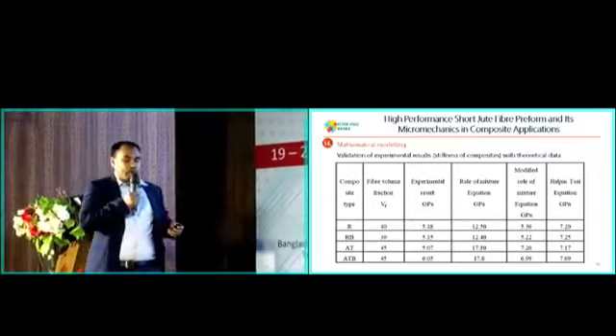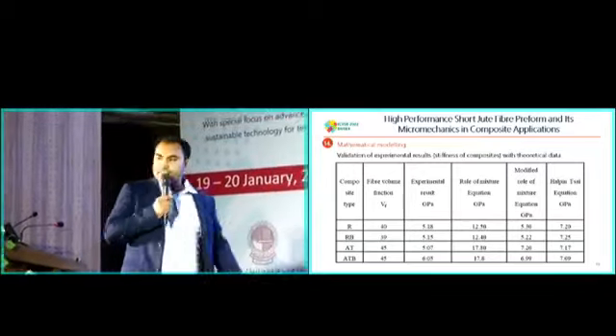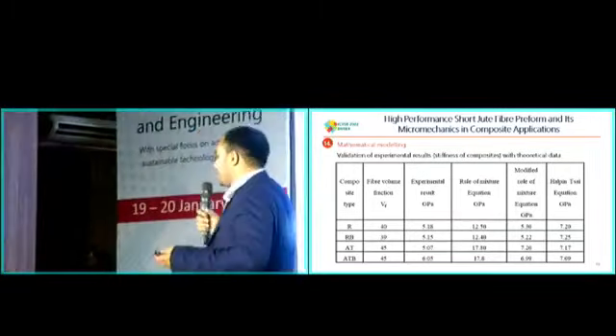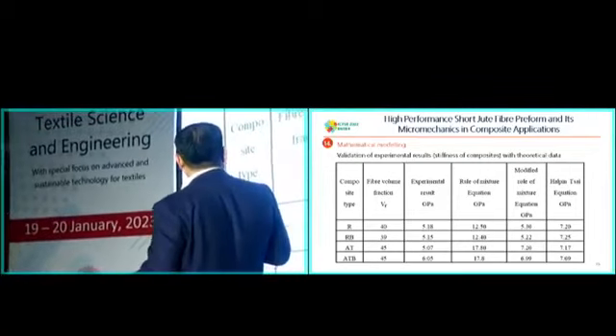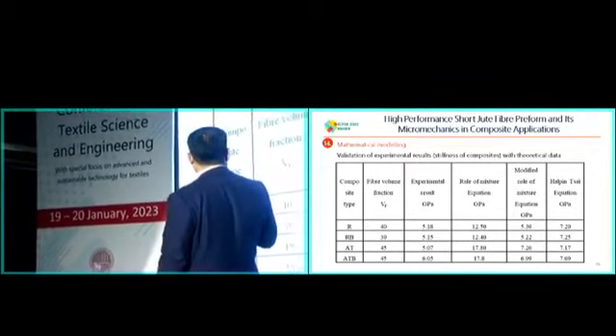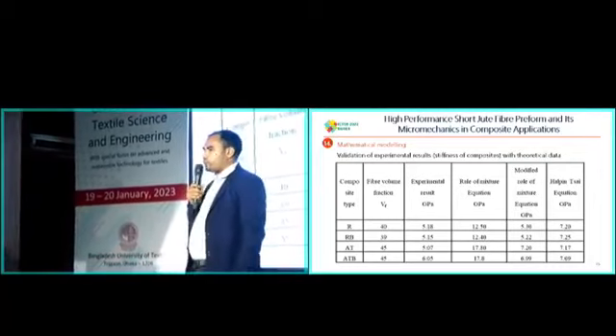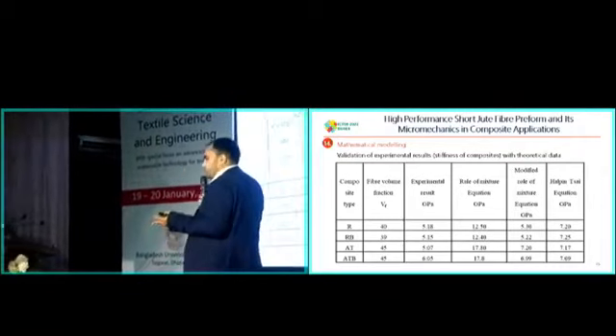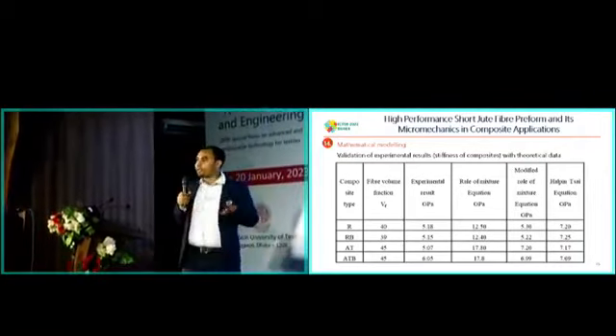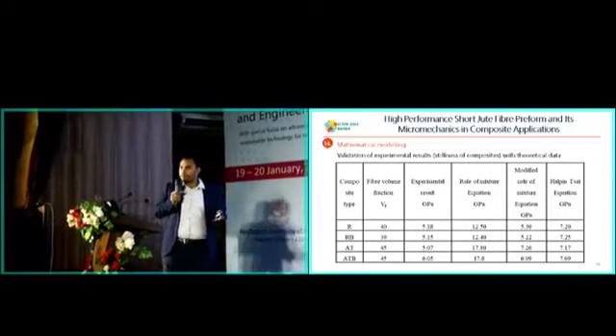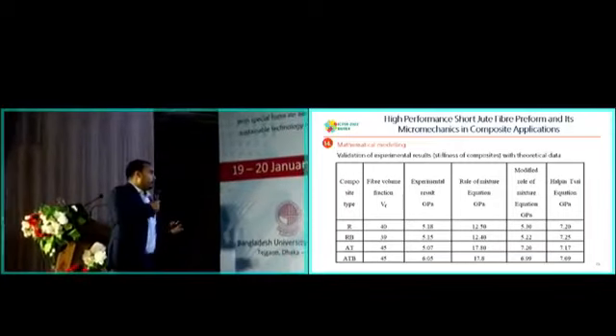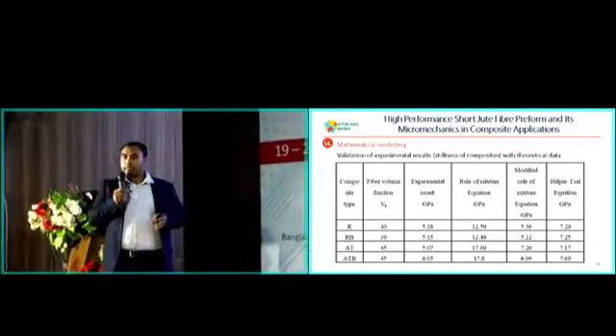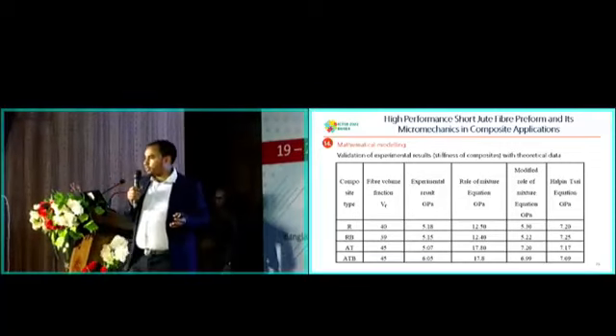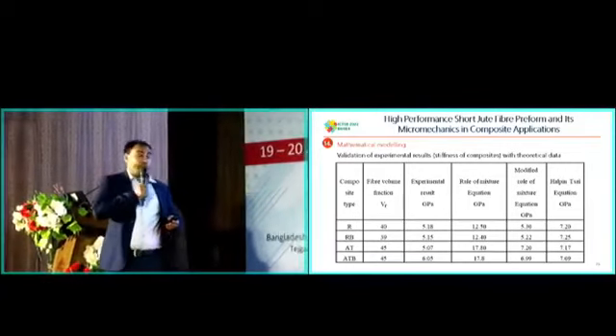Most importantly, one of the challenging factors is achieving the highest fiber volume content. In our work, we achieved a maximum of 45% fiber volume fraction. Ideally, when you use fabric or other traditional materials, you cannot get more than 25% or 30% fiber volume fraction. We achieved nearly 45% by applying individualization of the fibers and using the binder to make the preform with the novel architectures.